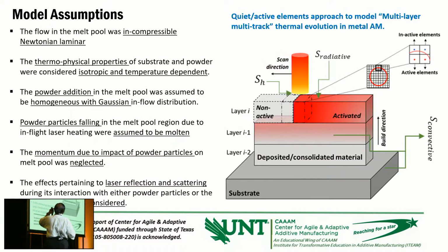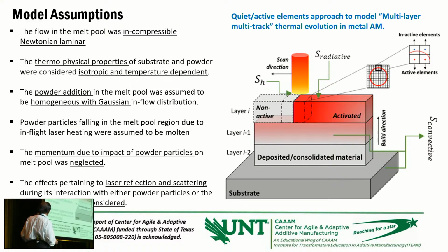So there are a lot of assumptions you have to make because these models are very difficult to develop, and there is not much information available in open literature. Those assumptions are given here. The melt pool was considered incompressible. The thermophysical properties are considered isotropic and temperature dependent. If available for some materials, you get the temperature dependent properties, but for many complex materials, you don't get the temperature dependent properties.